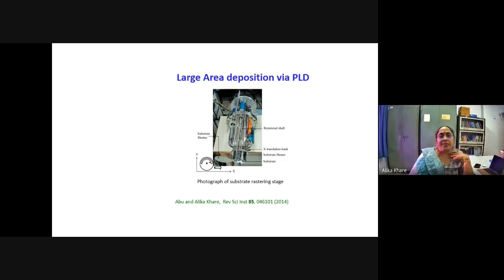So we tried to overcome that by connecting the substrate with a motorized stage in two dimensions. What we did was have two motorized stages coupled together: one along the x-axis, and the other by rotation. In this way, we were able to cover a large area of deposition.